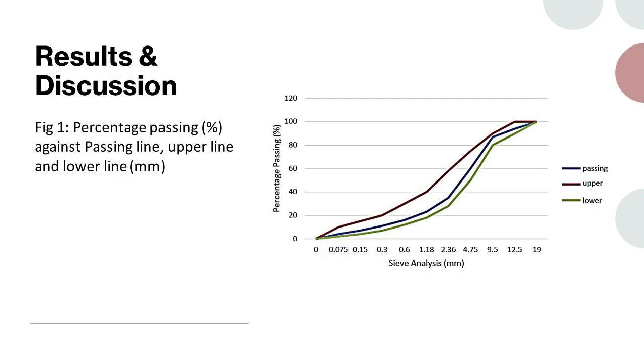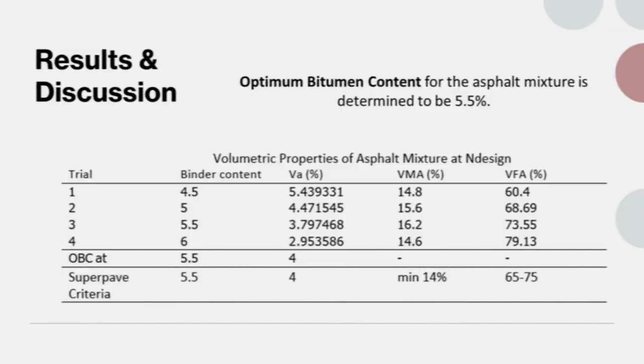The Superpave aggregate gradation consists of three components, which are coarse aggregate, fine aggregate, and mineral fillers. The OBC of the specimen was established using 12.5 NMAS. Trial bitumen contents of 4.5%, 5%, 5.5% and 6% were conducted using virgin bitumen to determine the optimum bitumen. Laboratory testing was performed on asphalt mix samples prepared with each of these bitumen contents. Properties of the trial blend were determined and tabulated, as well as the parameters of the asphalt mixture, which are air voids, voids in aggregates, and voids filled with asphalt.